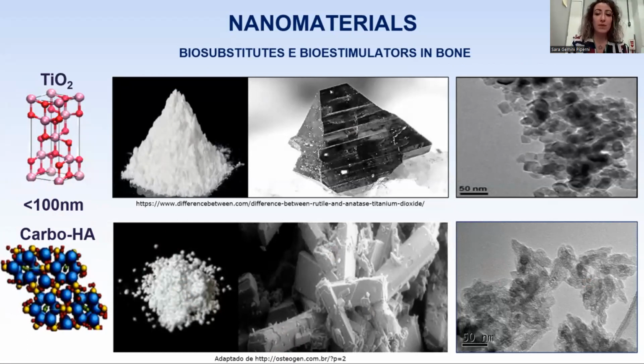its intracellular traffic. So what we define as nanomaterials, this definition is going to change. And till now, we consider nanomaterials as the material that have less than 100 nanometer size. But to work in these sizes, we had to develop some ultrasound-based dispersion protocols. And also we are working with the nanostructured materials, because these materials are going to form aggregates and agglomerates. So the nanostructured material is that one that have a primary particle that is less than 100 nanometers, and it forms agglomerates that can be also micro aggregates.